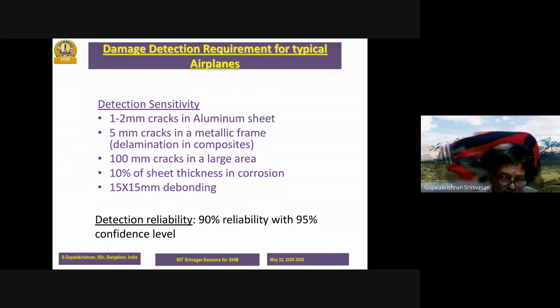and when there is corrosion, it will form pits, and it should be able to detect pits of 10% of the thickness. Pits will eat the material, and it should be able to detect 10% of the material thickness. And in a co-bonded structure, it should be able to detect 15 by 15 mm of debonding. And all of this should be repeatable, so robust that you should have 90% reliability with 95% confidence level. Still, we are not at this kind of reliability on online health monitoring, but offline, we can realize this reliability very efficiently.